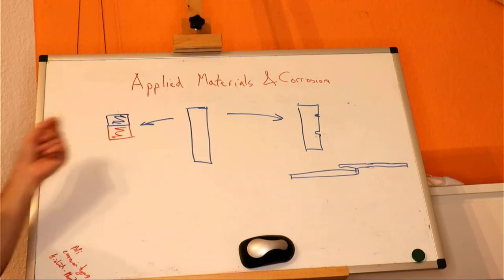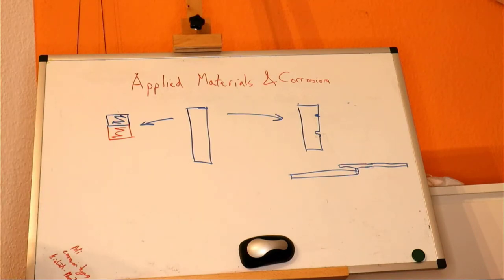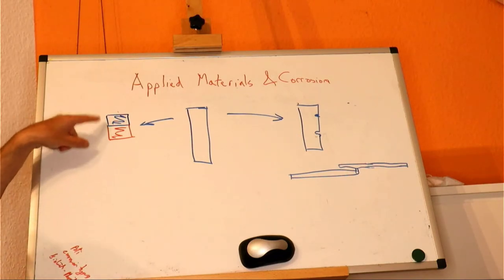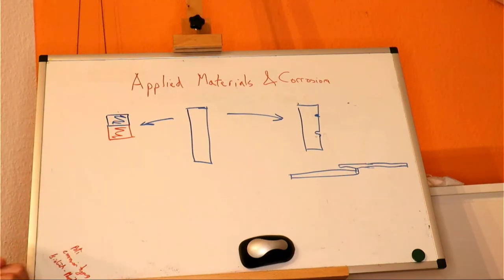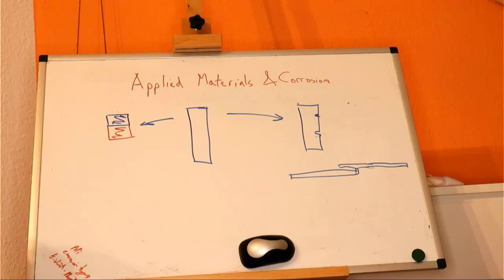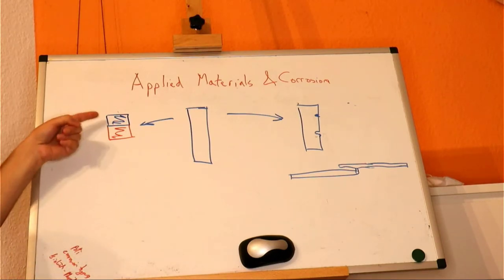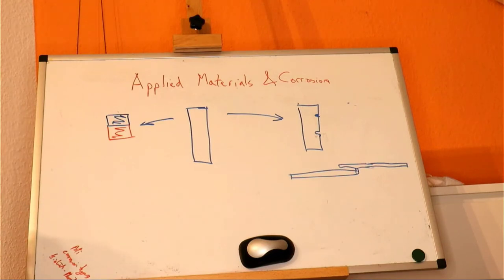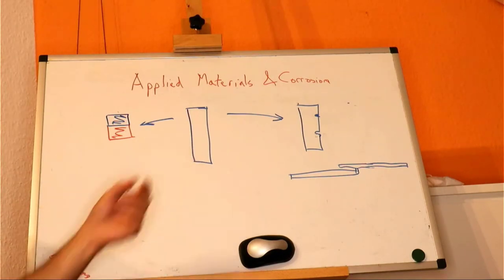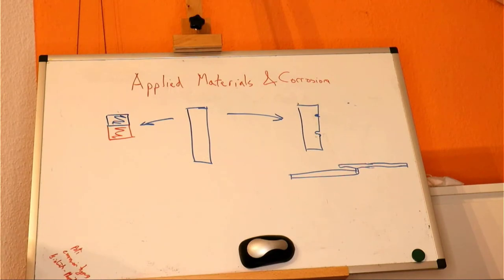However, the energy barrier for hydrogen formation on platinum is very low, so if we connect platinum to tin, whether it's directly or whether it's with a wire, which is what I did, it will cause the tin to corrode very quickly and hydrogen will form on platinum. Likewise, my fence in my garden is really badly designed. It's got zinc plated steel, which is pretty good, as we noticed, but it's connected together with stainless steel bolts.